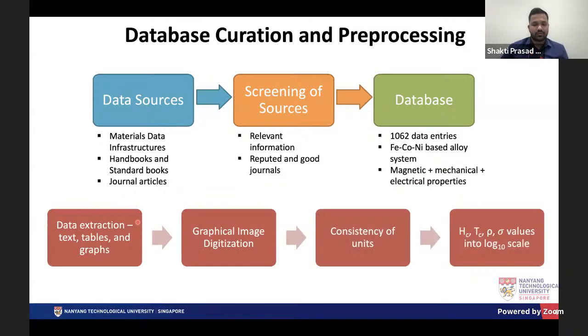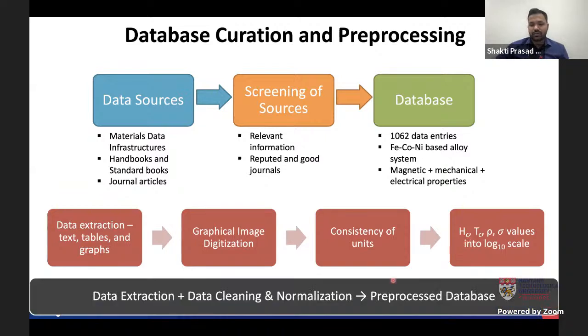The data extraction was done from text, tables, and graphs. There were some graphical images from which we were not able to extract the data directly, so we had to digitize those. This step was done using digitization software. Then the consistency of the units was maintained, and finally these properties, which are coercivity, Curie temperature, tensile strength, and electrical resistivity, were converted into log 10 values.